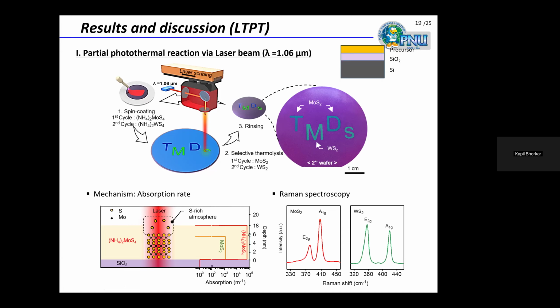And also the crystal size. Currently we are conducting an additional modification of our process: put this system in a vacuum chamber and finely control the laser parameters, to increase the grain size of the MoS2 and improve the mobility value. With the original process, the grain size is almost under 50 nanometers. But when we precisely control it, we can increase the grain size up to almost 90 nanometers, still